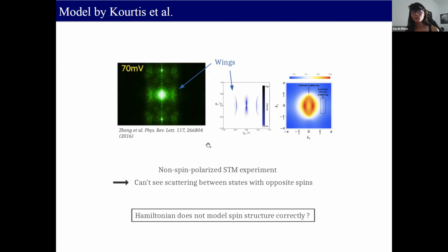Now, the thing is, this experiment was done with a non-spin polarized STM. And as I said earlier, this means that we should not be able to see scattering between states that have opposite spins. So what we concluded from this study was that probably the model that is proposed by Kourtis et al. does not represent the spin structure of Weyl semimetals such as MoTe2 correctly, and the Fermi arcs that you should obtain should actually not have opposite spin polarization.